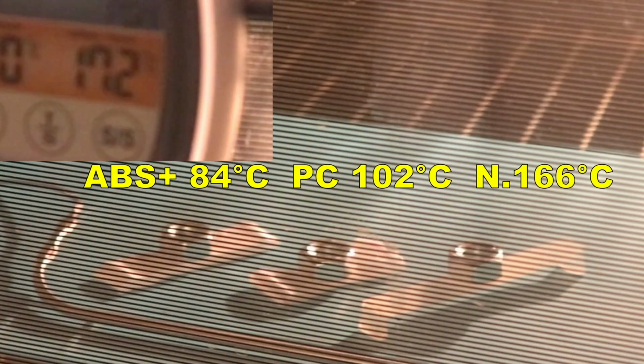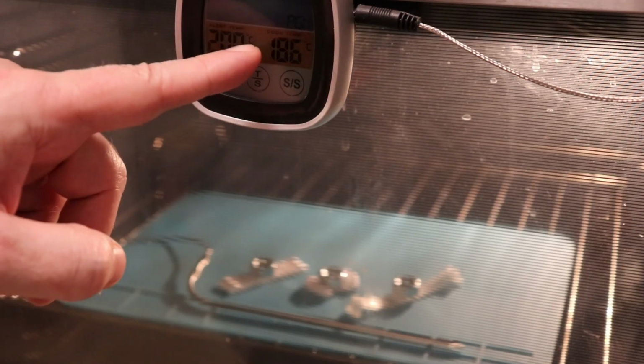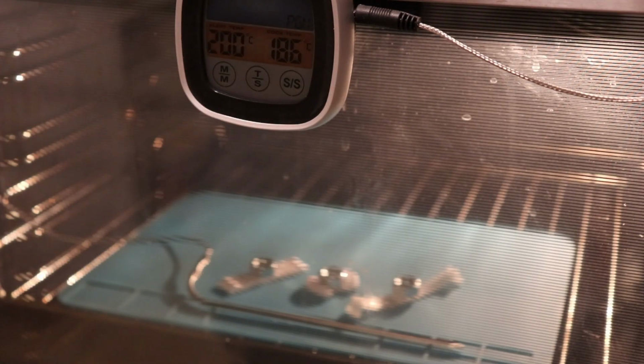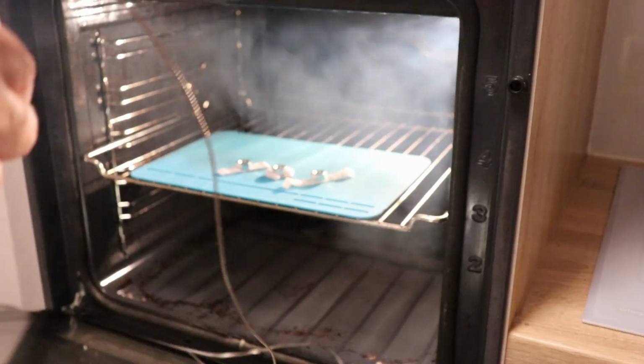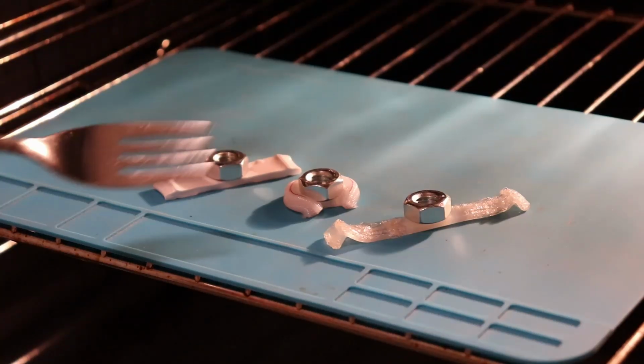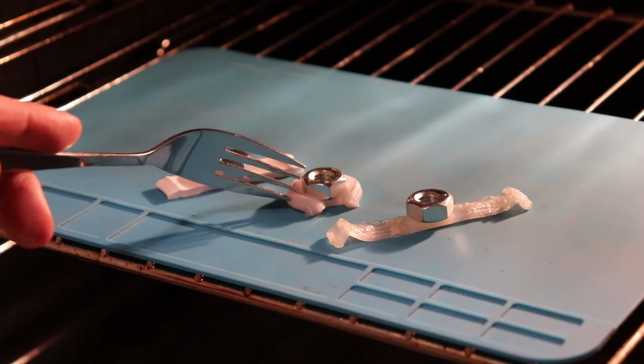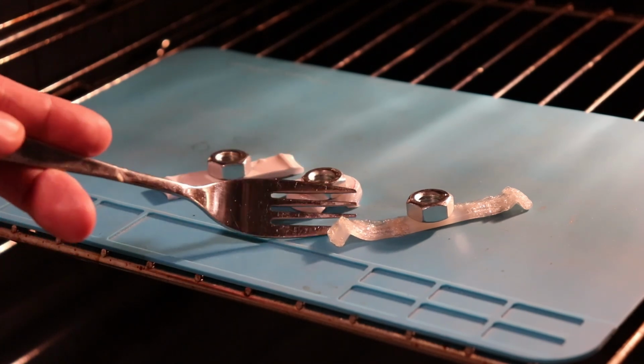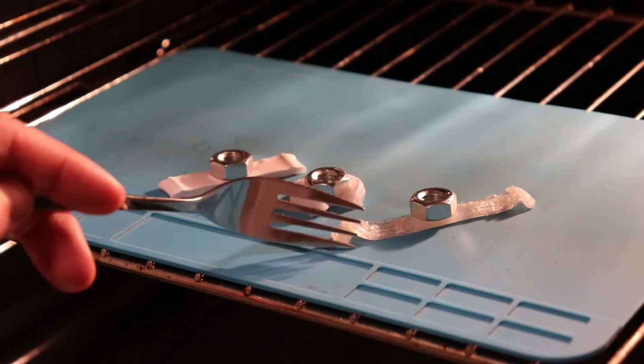I will follow the ISO 75 standard, but this is a comparison test anyway, and there were no surprises in the order for me, only I wasn't sure about the exact values. So the order was the ABS, PC, and the highest temperature resistant was the nylon. We stop the experiment now at 166 degrees Celsius. And this is the result. ABS, polycarbonate and very impressive nylon.